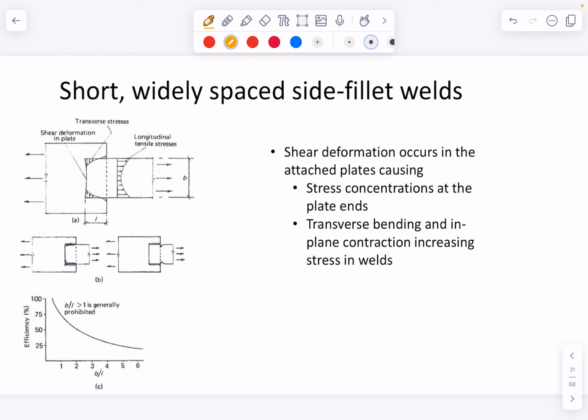Just something a little to the side, you might often see a tag welded onto something for whatever reason. There is a limiting value of B over L. Well, I guess it's not limiting, it just becomes pointless. If B over L is 1, so I've got a 50mm wide plate embedded by 50mm, then I can utilise about 70% of the capacity of that tag. If I've got a 200mm wide plate that's only embedded 50mm, then I'm probably down around 35% or 25%, whatever that line should be looking like. Yeah, more like maybe 30%. Because the stress can't propagate from the weld way out here sensibly and support the middle, okay? So you just need to be mindful of that.